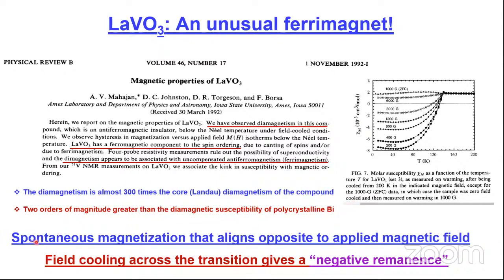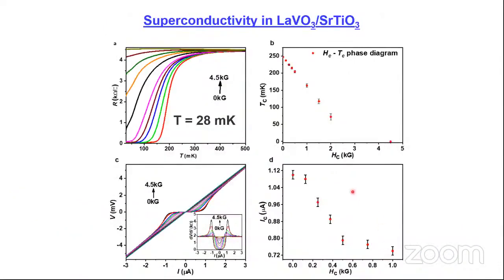So what was seen in these experiments is that it has a spontaneous magnetization, and that likes to align in a direction opposite to the applied magnetic field in which it is cooled down across 138 Kelvin. So field cooling across the transition gives a negative remanence for this compound. And I will show you that this negative remanence actually plays out nicely in the interfaces.